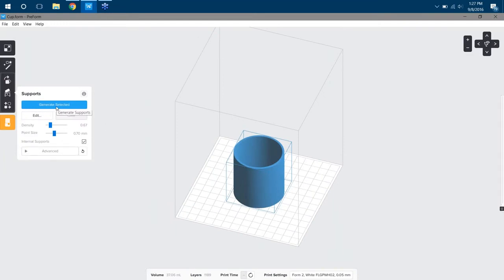Most of these are pretty simple. You generate the supports for the models you have selected. If you don't have a model selected, you'll have the option to generate supports for all the models in your scene. These are direct edit, so this button here, edit, allows you to directly edit the support placement for each model. Clear lets you wipe them away. Density changes the amount of supports, and point size, like I said before, is increasing or decreasing that touch tip size, which is increasing or decreasing the strength of the bond that's actually holding the scaffolding to the part.